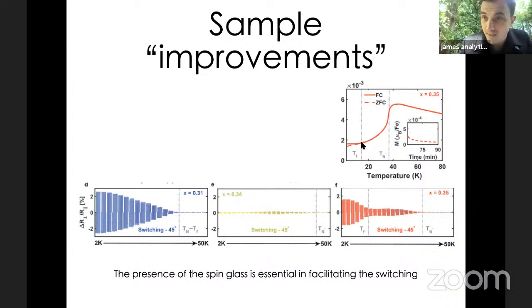But a spin glass does know what conditions it was cooled in. And that's what we think is happening at this intermediate temperature. That's where the spin glass is somehow freezing. And we can look at dynamics, the other signature of spin glasses that you expect, some long time scale relaxation. That's what I've shown on the inset here, that around this temperature is where this long time scale relaxation seems to onset. And that's where the switching somehow blows up. That's where you start to see this growth over here.